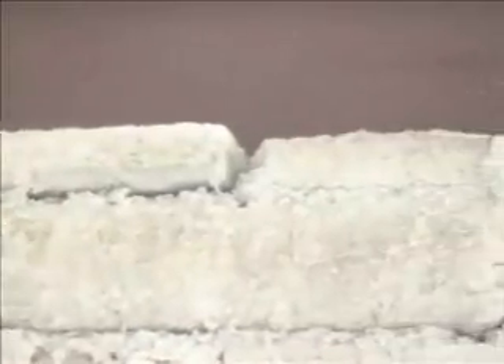Here we kind of overkilled it with big I-beams — I had a bunch left over from my house and we just butted those blocks up to the I-beam. The problem is it's great strength, but whenever you go and plaster over that metal I-beam, you've only got a quarter inch of plaster over it. All I can tell you about cement is it turns gray, it gets hard, and it cracks — and it always cracks to the easiest point. Right there where you've got that quarter inch, it'll crack right along that beam. So what we've done now is instead of using that heavy gauge I-beam, we've gone to a four-by-four square steel tube. That way, with our ten-inch block, you still get a couple inches of bite on each side — you completely encompass that piece of steel, plaster over it, and it's eliminating a lot of the cracking.